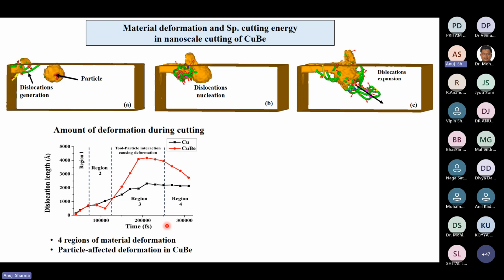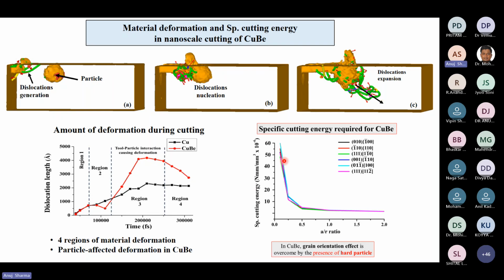If we look at this dislocation length graph, we can see that for copper and copper beryllium in the particle region, there is a lot of dislocation taking place. That means in this particle region, a large amount of subsurface damage takes place due to the formation of long dislocation loops. And here the specific cutting energy was plotted, and it was seen that almost all the graphs were overlapping. So it can be concluded that in copper beryllium material, the grain orientation effect is overcome by the presence of the hard particle.